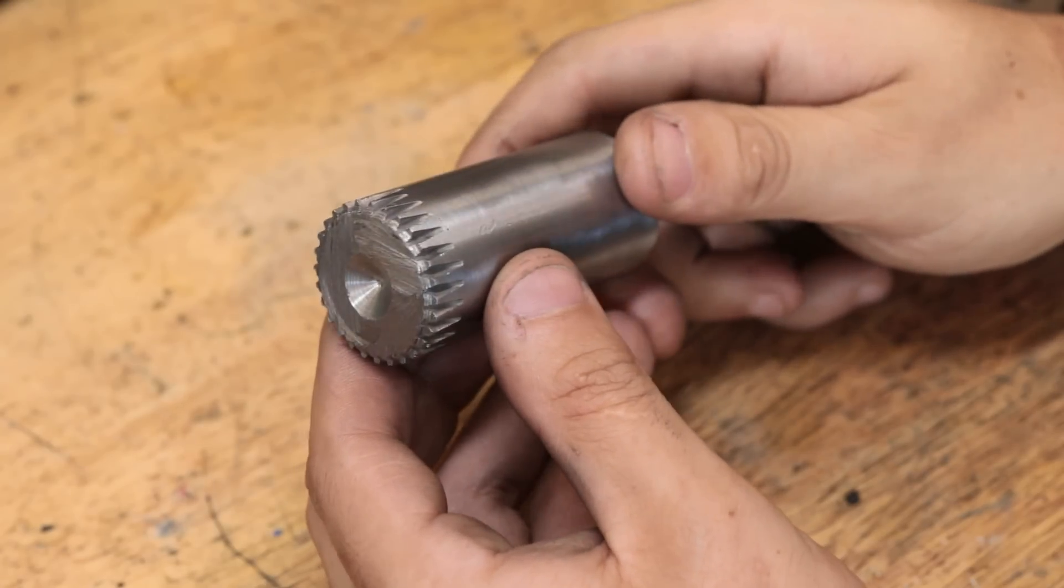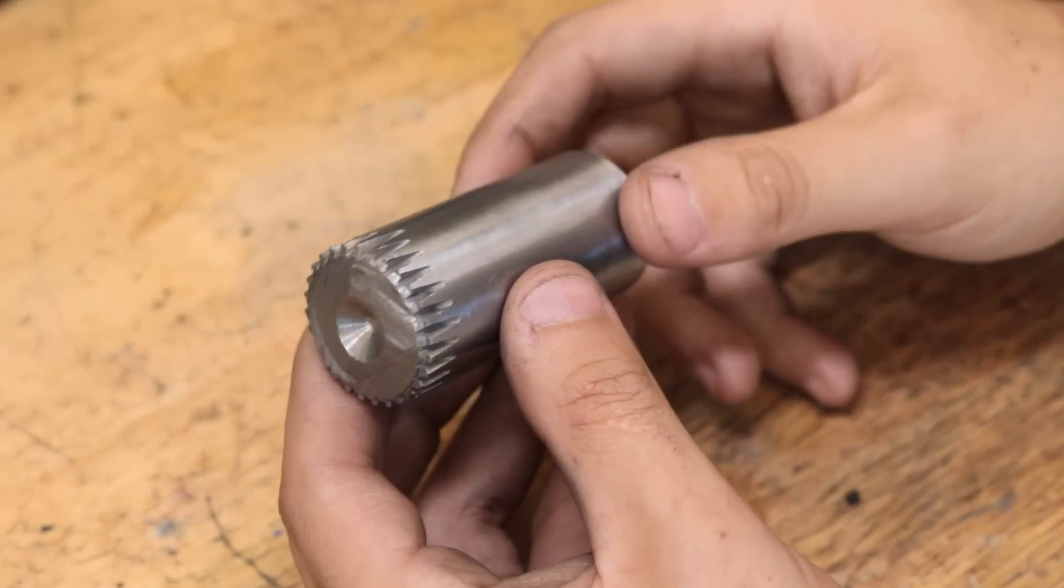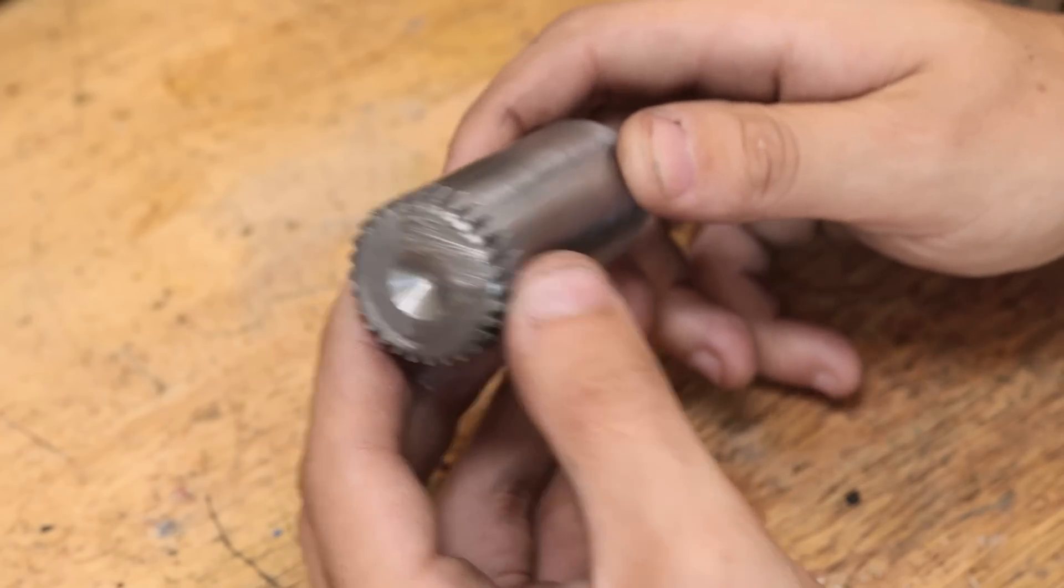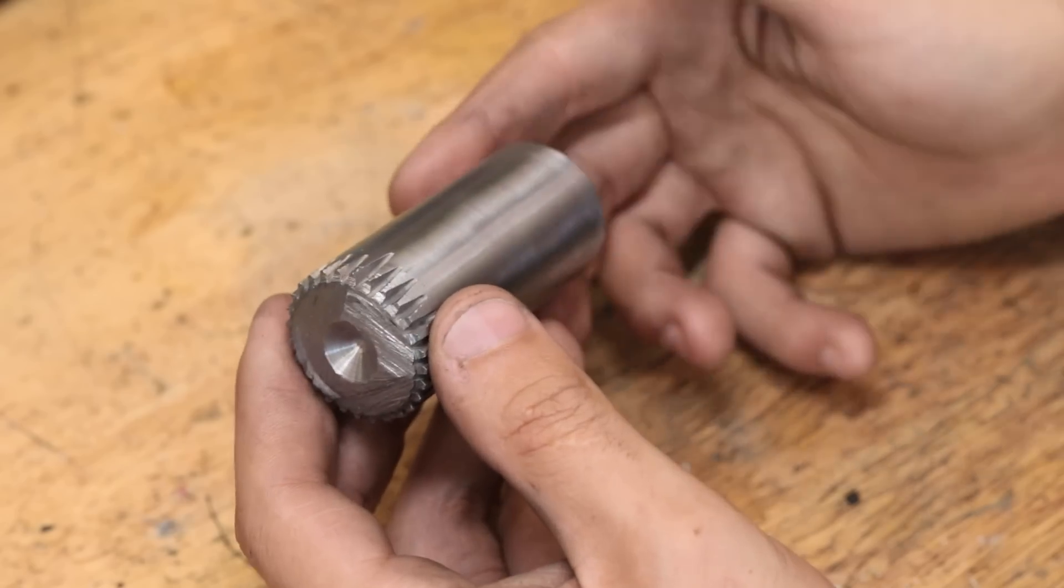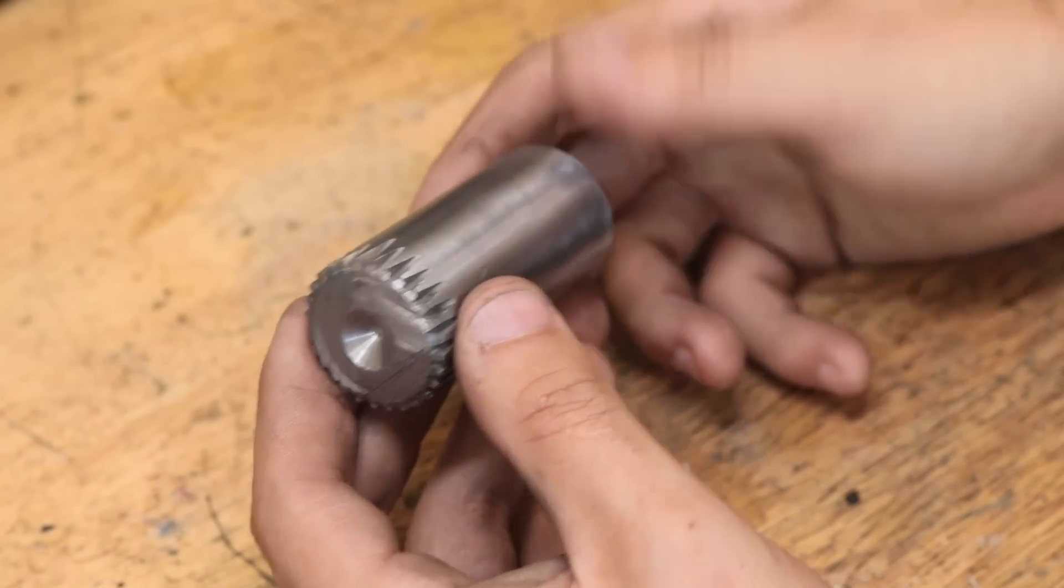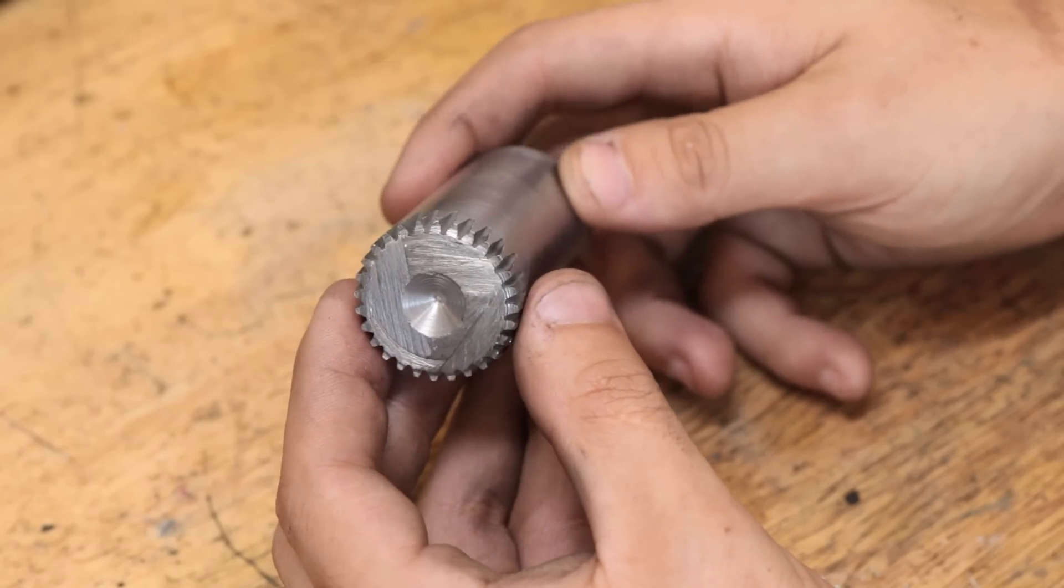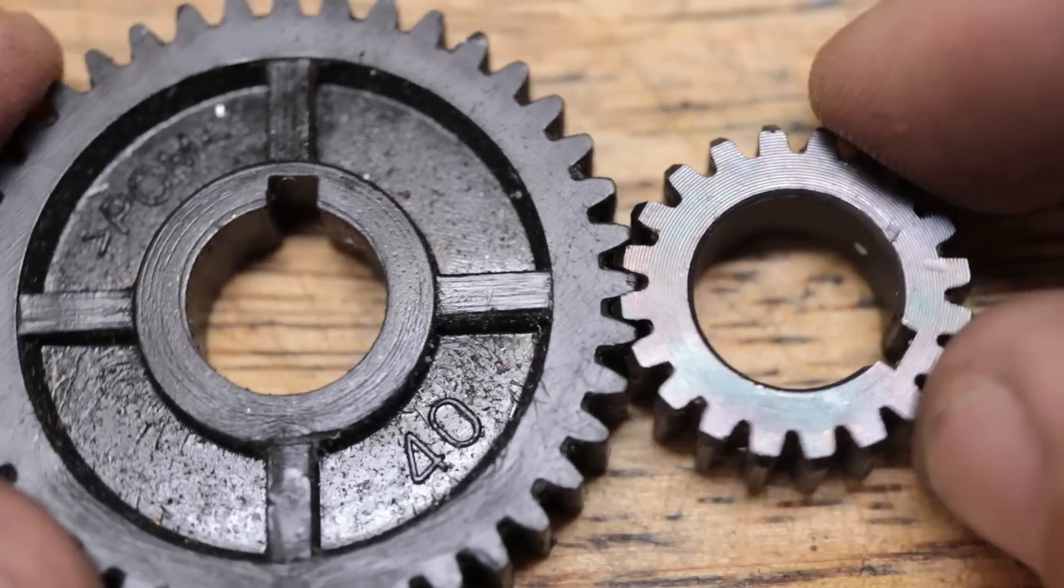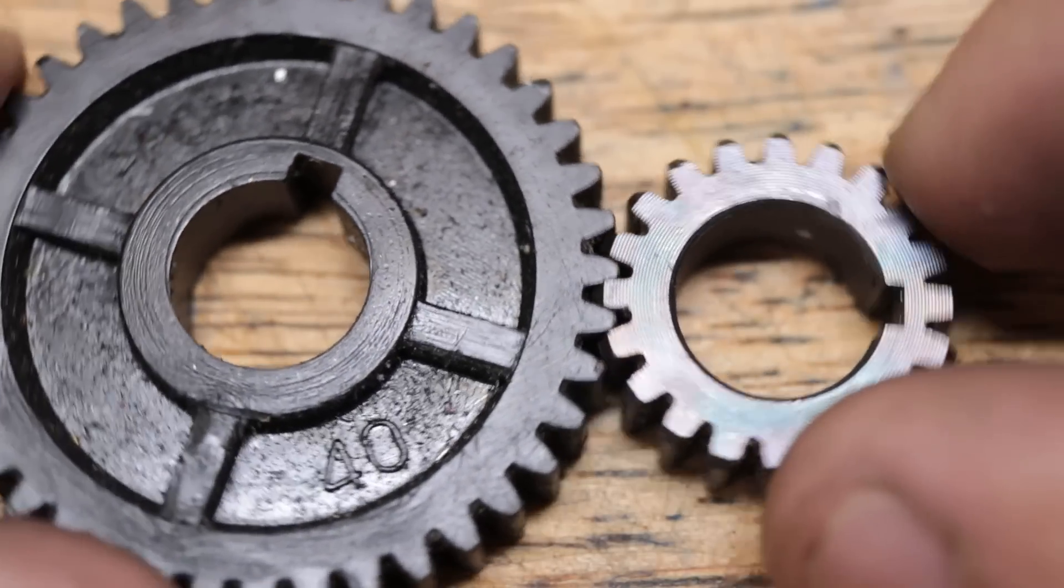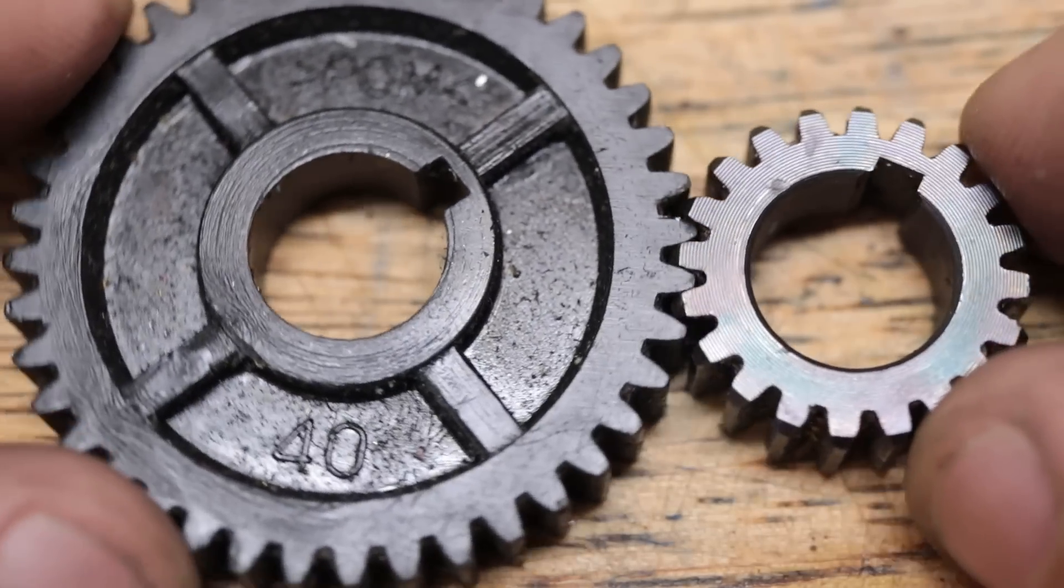The first characteristic is pretty straightforward. It has a high tensile strength, which is usually a good thing to have. It's not the strongest alloy, but it's almost twice as strong as a low carbon steel, and that's despite the fact that this alloy has almost no carbon in it. And in a practical sense, it means that when you case harden a part, let's take a gear tooth as an example, the material that is making up the bulk of the gear tooth, and that's taking most of the load, it's going to be made from a higher tensile steel.